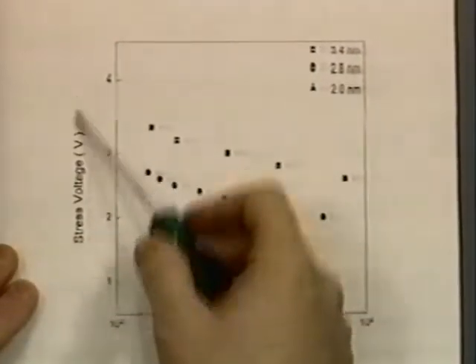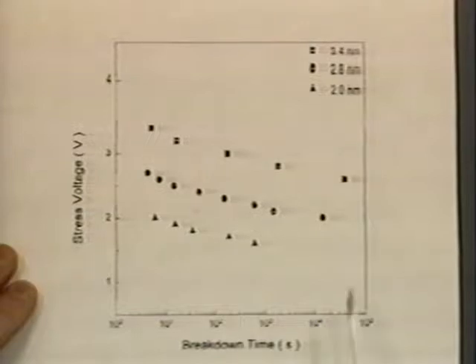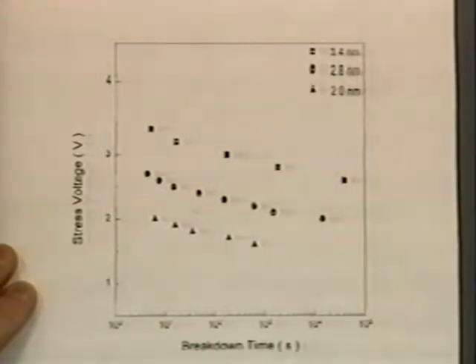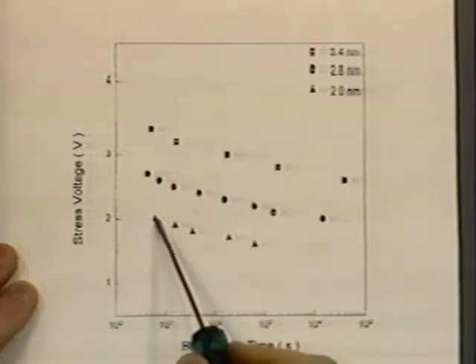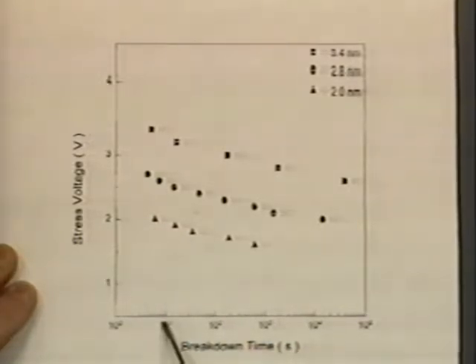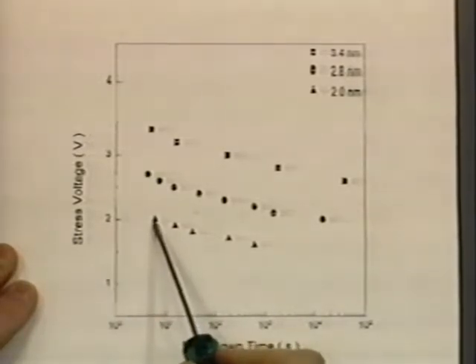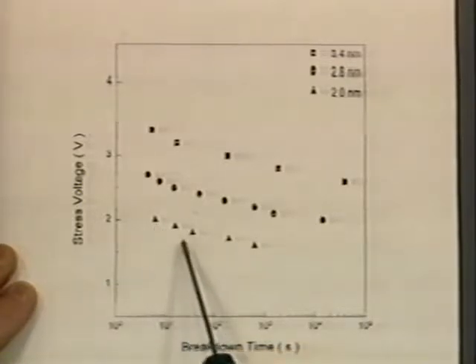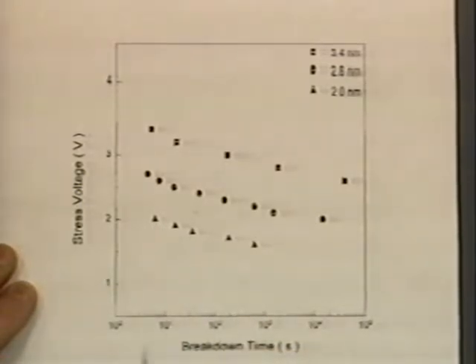So here I plot stress voltage versus breakdown time for 3 different thicknesses. Let's say we sit at 2 volts. On the thinnest oxide, in 10 seconds, the device breaks down. Now this is an average of about 20 devices for each one of these points. But if we look at the 28 angstrom oxide and we sit for 10 to the 4th seconds, that's on average, before the device breaks down.